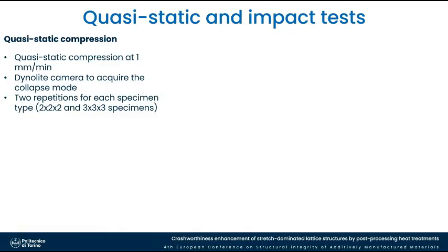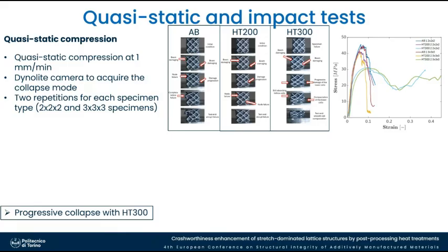Then we tested the lattice structures, starting from quasi-static compressions. We did these on both 2x2 and 3x3 specimens with the three heat treatments, and we acquired the collapsing mode during the test. What we observed basically was that in the as-built and at 200 degrees, we still get a brittle failure, a stretch-dominated behavior of the structure, while at 300 degrees, we obtain a progressive collapse.